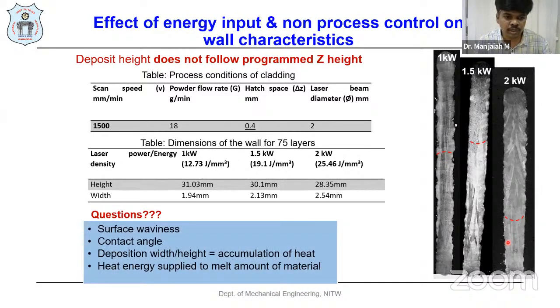We have to control the surface waviness as well as wetting angle, which controls the deposition width and height as well as accumulation of heat. Means the heat energy which is supplied should melt the required amount of material, how much quantity of material is to be melted. That has to be optimized, even with numerical simulations or with many trial and error experimentations, that will control these kinds of defects.